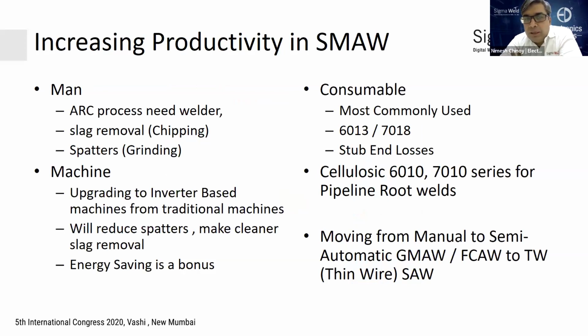If you want to increase the productivity and efficiency in these processes, you need man, machine, and consumable, all three to be improved. If you look at the man, arc welding needs a welder. It can rarely be an automated process. It's a non-automated process. For slag removal and spatters, you need to have chipping and grinding. You can improve this by upgrading to inverter-based machines from the traditional machines such as transformers and rectifiers. This will help reduce spatters and make slag removal cleaner. Also, energy saving is a bonus. You save close to about 30 to 60% energy if you move to inverter-based from the traditional equipment.